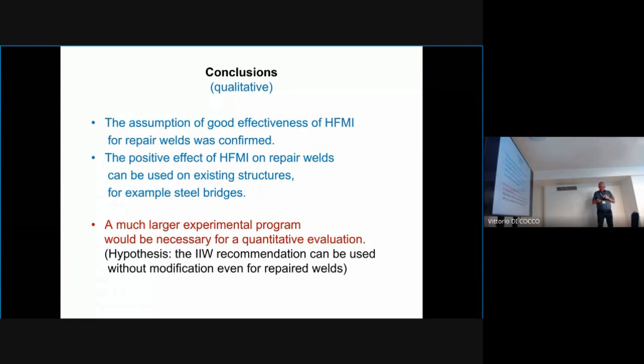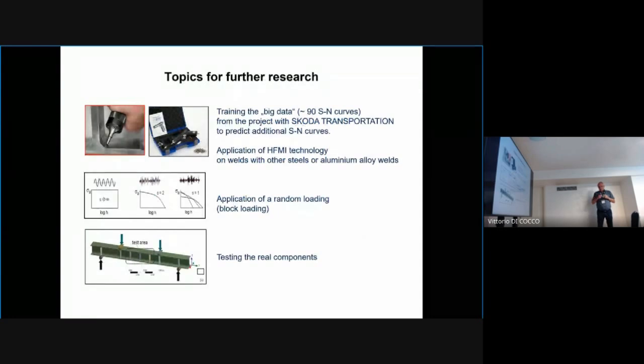This is a topic for further research because we would like to continue in this type of research because we have 90 very good SN curves which were created from 12 to 20 test specimens. We hope that we will be able to perform the training on the data. Also, SN curves created for materials, different thickness plates, etc. And we would like to try to predict the additional SN curves for other materials and other thicknesses, etc. And predicted values will be tested experimentally again to say that our neural network is working well.